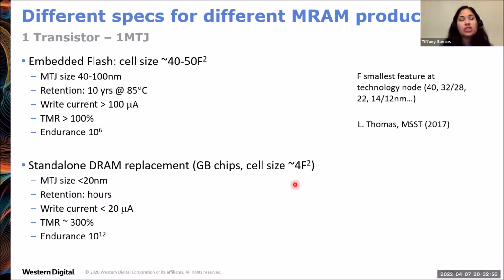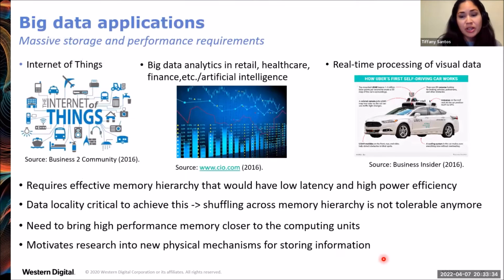But if we want to push and advance this memory toward being more high density, for example, a standalone DRAM replacement, then we're going to need very small magnetic tunnel junction sizes to get that high density. So the goal is 20 nanometers or less, a write current less than 20 microamps, TMR values very high, approaching 300%, and endurance 10 to the 12 cycles, kind of reaching more towards that unlimited endurance.